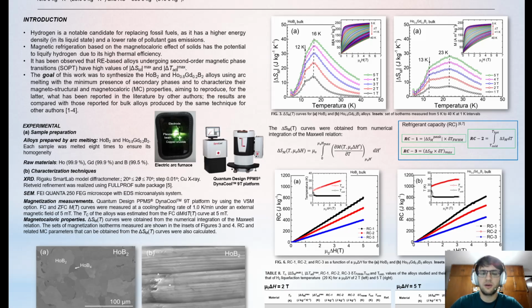And we can also see peaks at 12 and 13 Kelvin in both figures, which are associated with the spin reorientation of the system. For the gadolinium doped alloy, in the curves for 1 and 2 Tesla, we can see a plateau shape between the 13 and 23 Kelvin. A highly desirable feature for these applications. As mentioned in the experimental section, these curves were obtained from a set of isotherms that we can see on the insets, integrating them with the Maxwell relation.